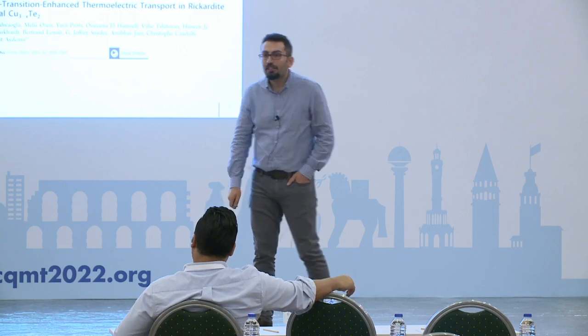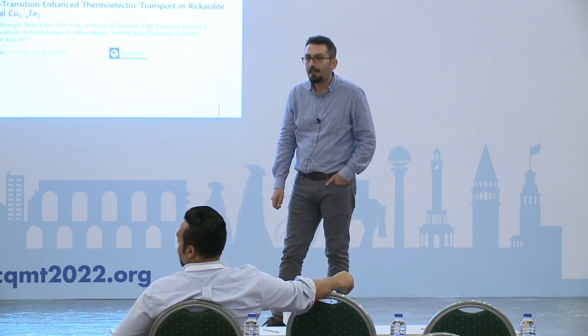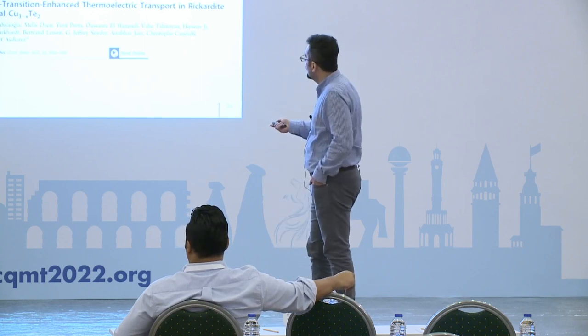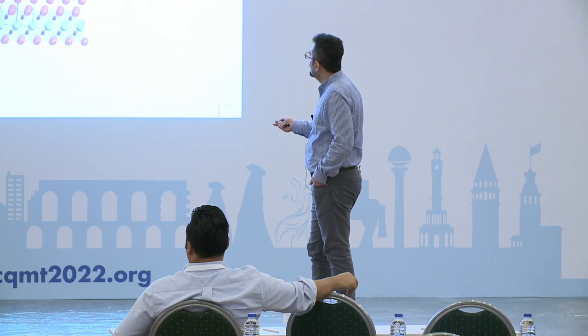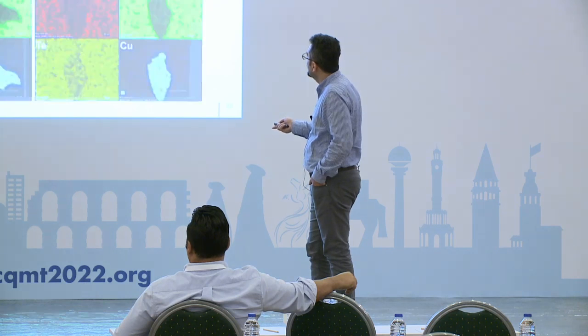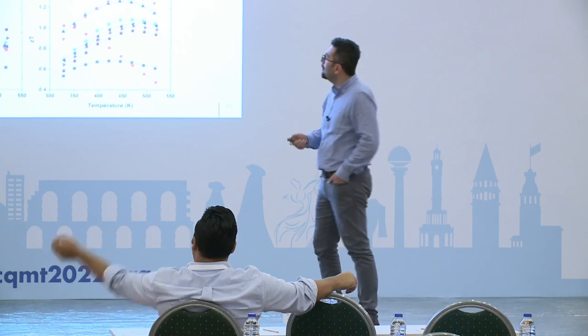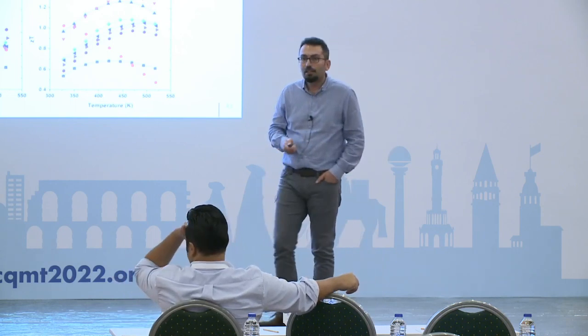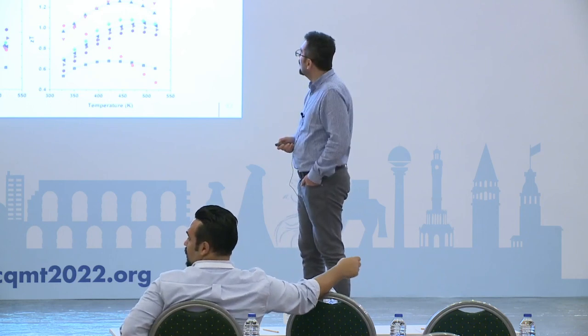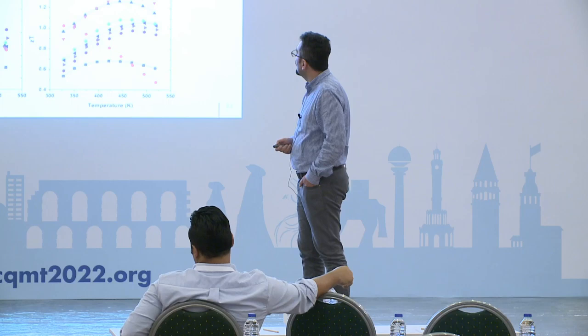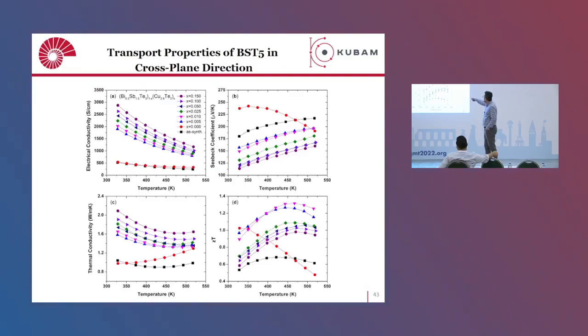Okay, so you had a figure where you showed that with 0% copper telluride, the temperature trend was down in the figure of merit. Let me show. It's a bit later, I think. Here, yes? Now I have a very simple question. Both figure of merit and Seebeck coefficient have exactly the opposite temperature trend at 0% copper telluride and not 0%. This one, the red one, sticks out. Do you have some kind of simple, quick way to understand that? Yes, sure. You mean the Seebeck coefficient going down as opposed to the others. Yes.